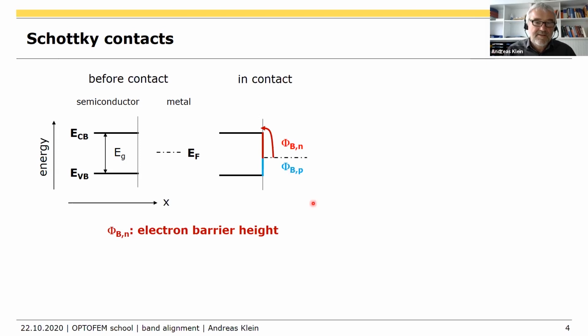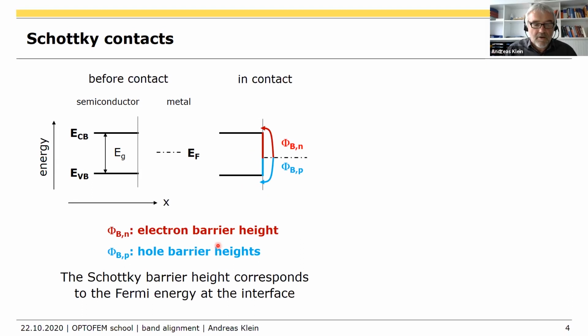The same for the holes. You have a potential barrier for the holes, and the barrier height for the holes is this one. And the sum of the two, that's simply the band gap. So if you measure the barrier height for electrons and the barrier height for holes, and the sum is not the band gap, something is strange. Okay, so that is important, and people very often do not understand this language, but the best definition of the Schottky barrier height is that it corresponds to the Fermi energy position at the interface.